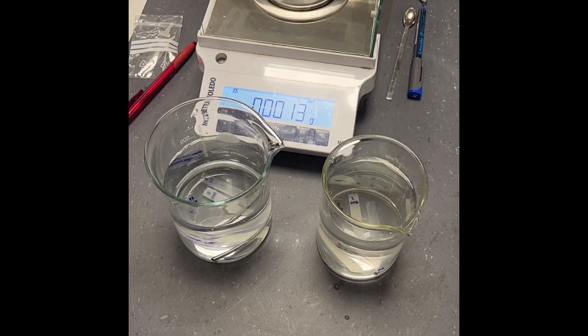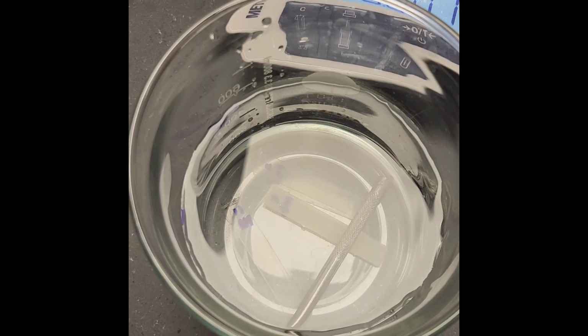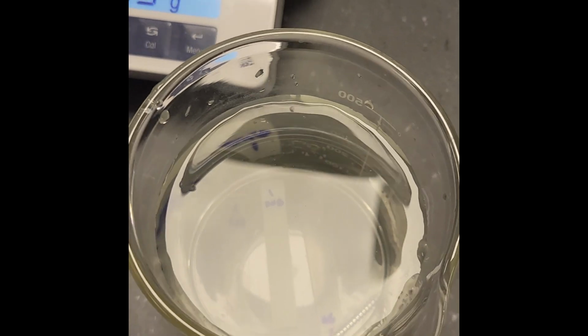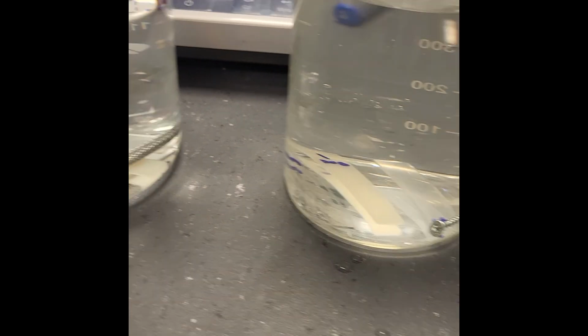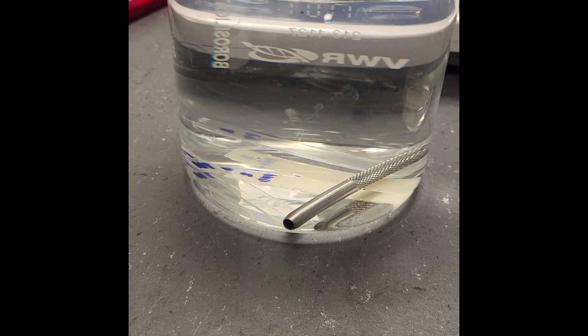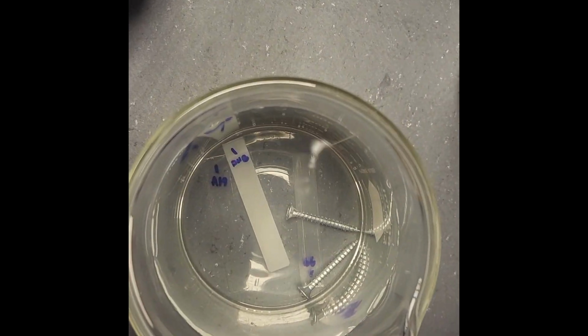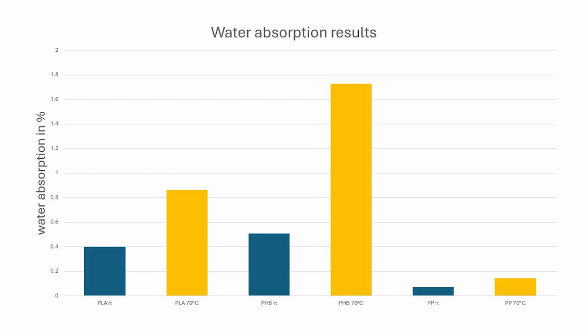So for this, a water absorption test was carried out. The samples were set in a crystallizer filled with distilled water and left for 24 hours. We simulated two different environments, one at room temperature and one at 70 degrees Celsius to simulate a hot liquid in a cup. The weight difference before and after the experiment has been measured. In general, we can see that the water absorption is lower at room temperature than at 70 degrees Celsius, and this is the case for all three materials.